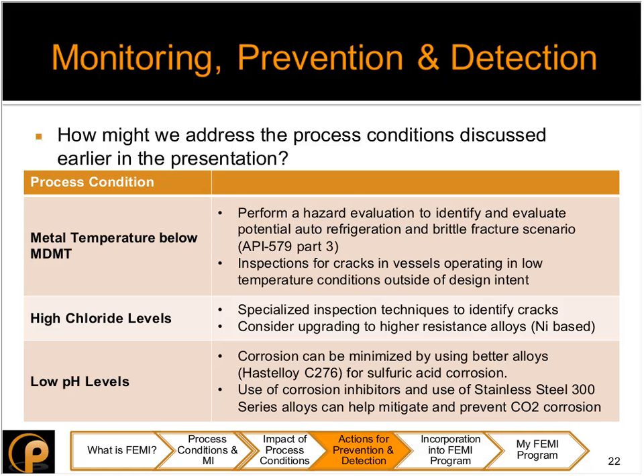Now going to lower pH levels. Corrosion, you can minimize sulfuric acid corrosion by using better alloys, like I said, and Hastelloy C276 is really resistant towards sulfuric acid corrosion. For carbon dioxide corrosion, what you can do is the use of corrosion inhibitors or the use of 300 series stainless steels can help mitigate and prevent CO2 corrosion.